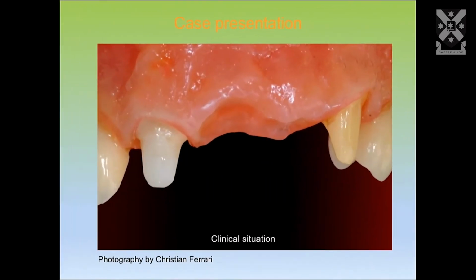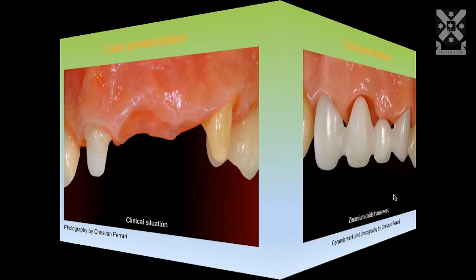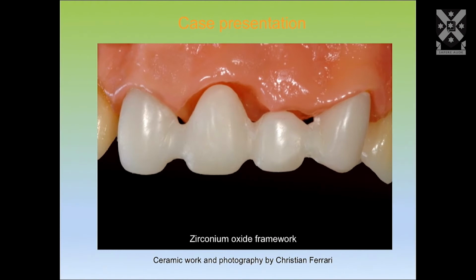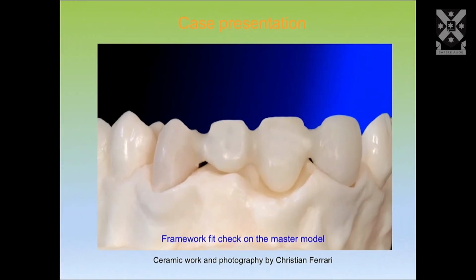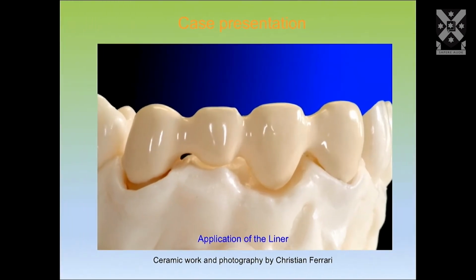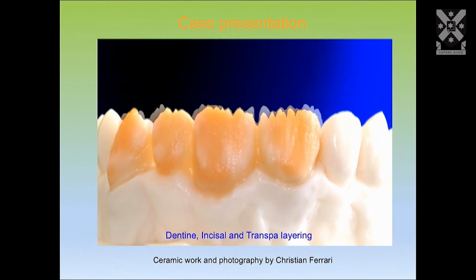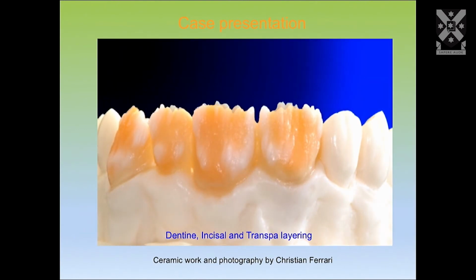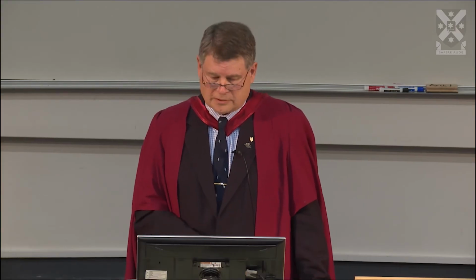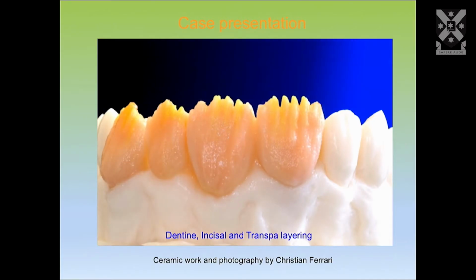So just to show you an example, here's a case where you have a central, a lateral, and a canine, i.e. your 2 front teeth and the one next to it and your canine. There's the all-ceramic zirconia substructure being tried in the mouth. Back on the cast, the dental technician is now going to make it. That's the first layer has been fired on. And then we start to layer these porcelains, which are powder mixed with a liquid, and we take a paintbrush, and we start to build up the different colors and translucencies. It's like painting with glass. And this is slowly built up until we get the shapes and the nuances of color in the right places.